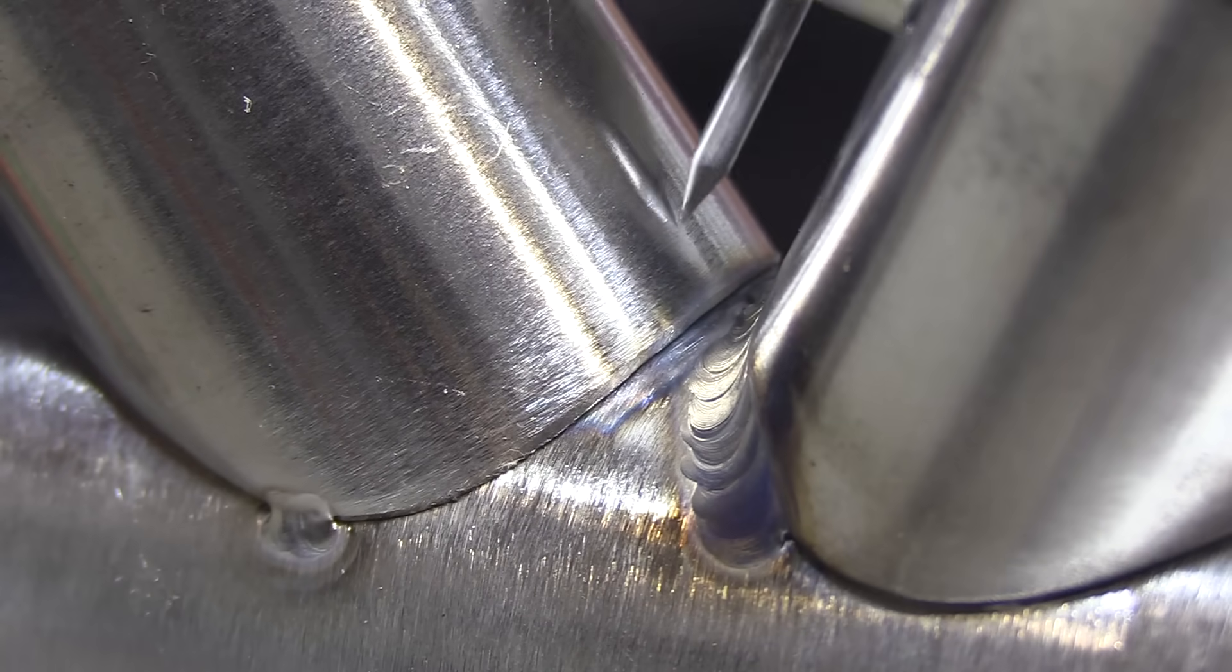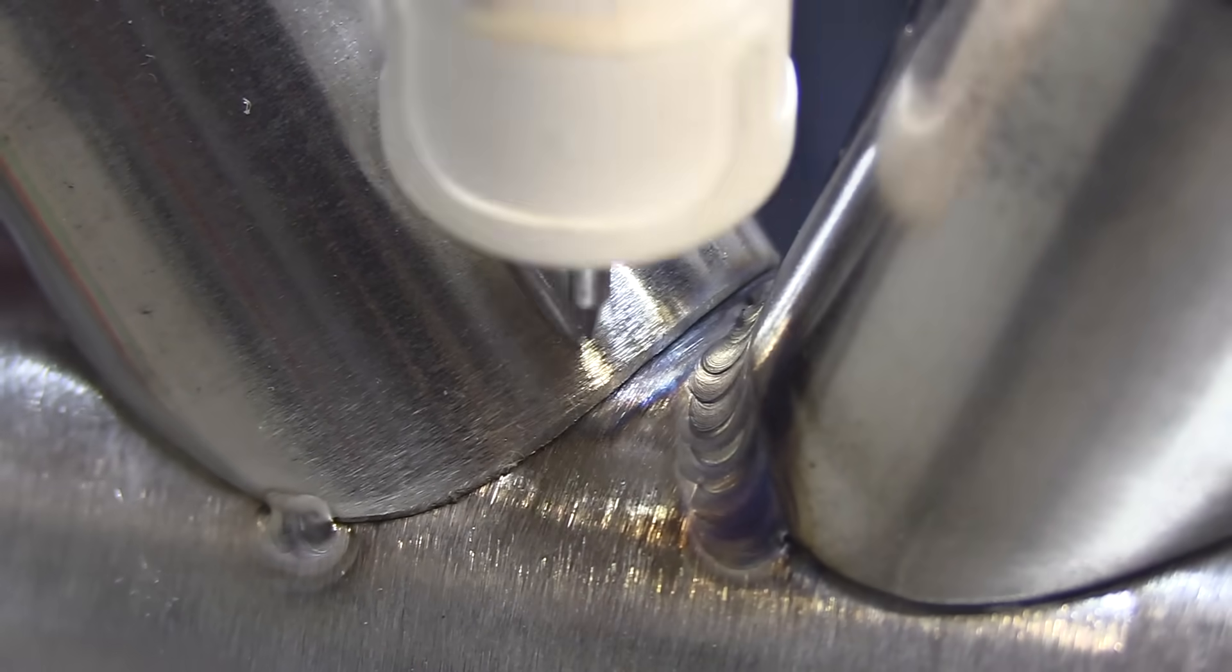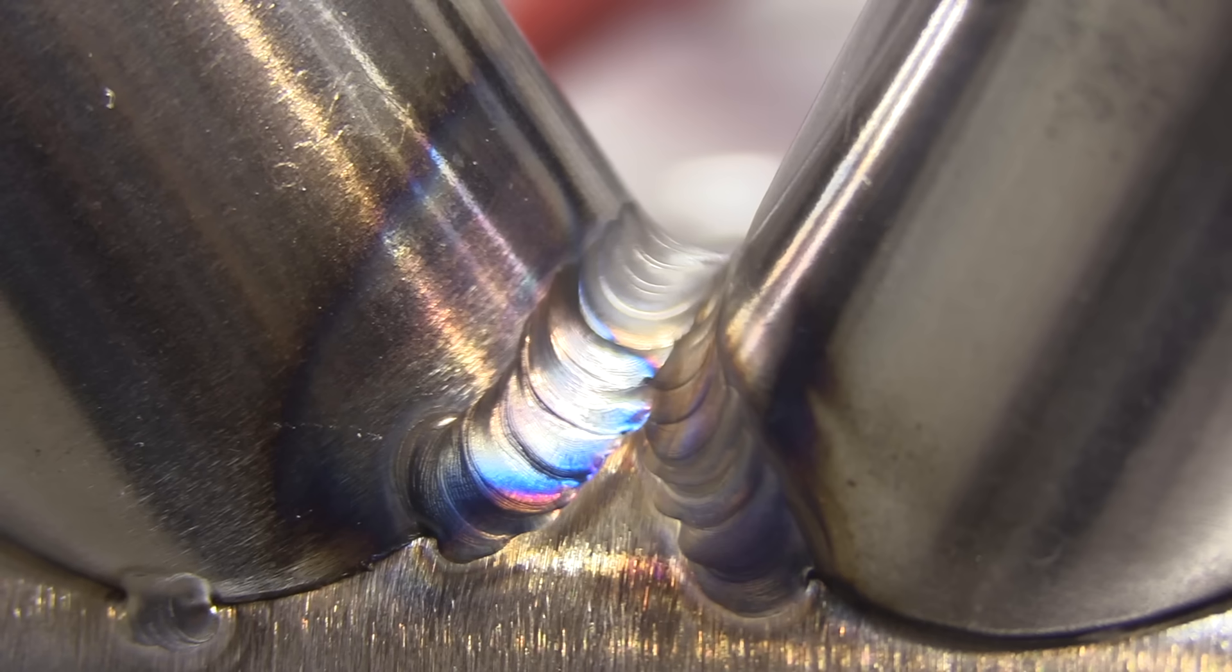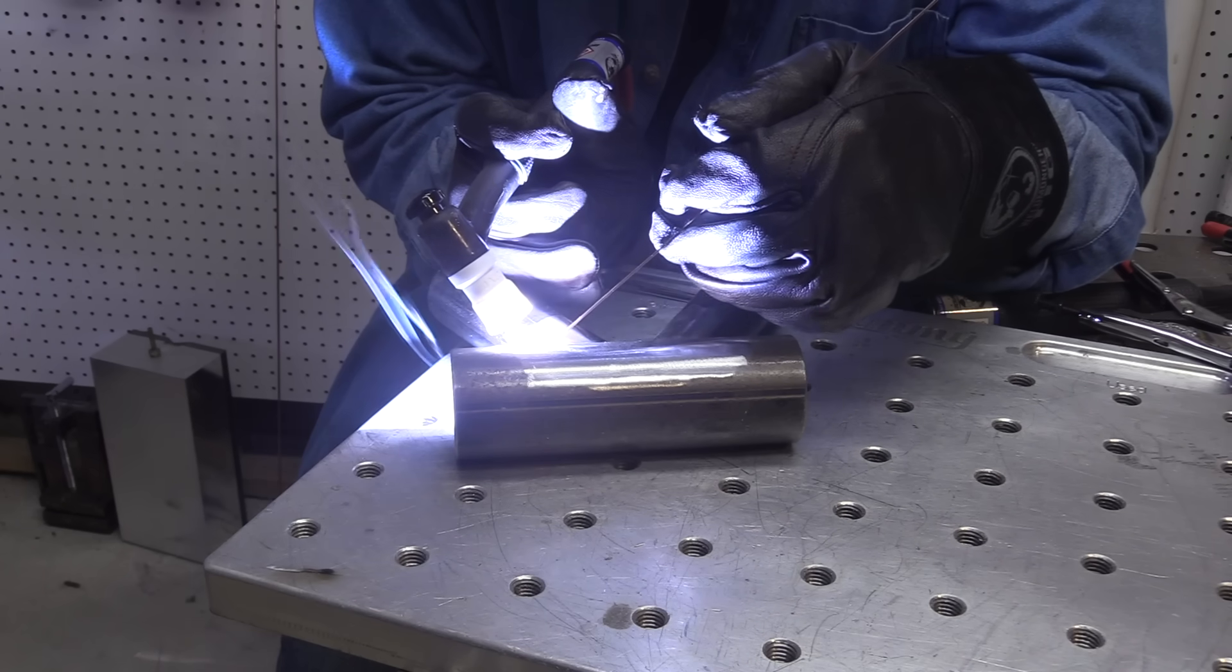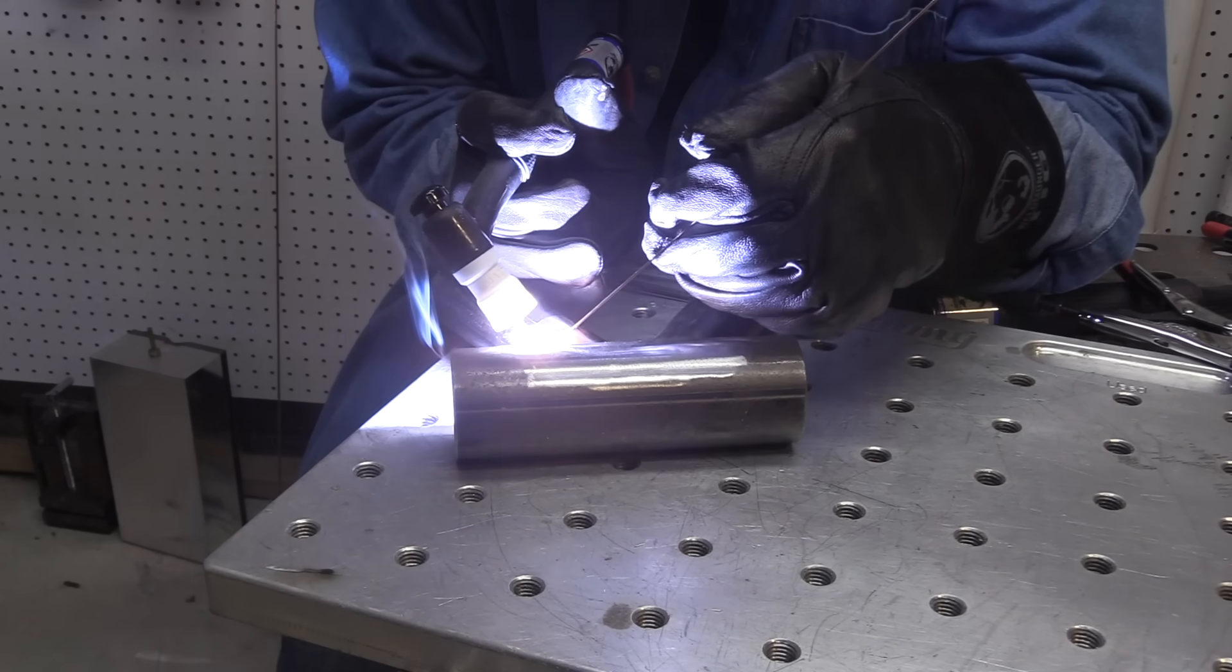Having clean bright metal, not just polished over mill scale, is very important for TIG welding. Another thing we'll show in detail in just a little while. Right now I'm about a five-eighths long stick out at 20 CFH. Cup's working fine but I'm a little shaky—hopefully I'll get better as we go. I'm using 0.045 ER70S2 filler rod on this.